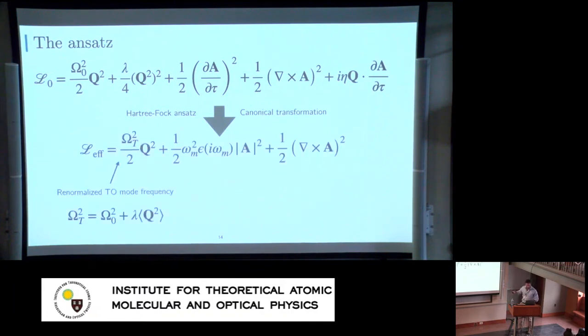Well, essentially, you can do Hartree-Fock on this non-linearity here. You can do a couple mathematical steps, I'll spare you the details. The point is that you end up with a simplified theory, which involves this renormalized phonon stiffness, which includes not only the bare material contribution, but also contributions from the fluctuations.